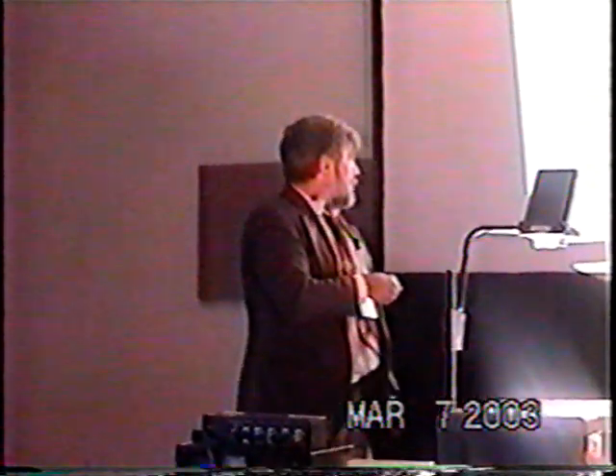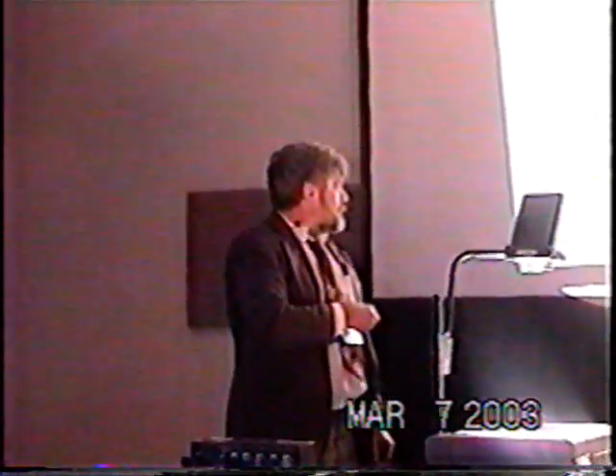A research effort developed within the framework of a cooperation between ENEA and SRI was mainly oriented to perform electrochemical experiments to investigate the emission of X-rays during electrochemical hydrogen loading of thin metallic films of Pd and nickel, and to monitor the inventory of marker elements in the electrochemical cells. So they put particular things in, and they looked carefully at how they changed. They also did a replication of the double structure cathode experiments, looking for helium-3. This was the experiment that had been done before.